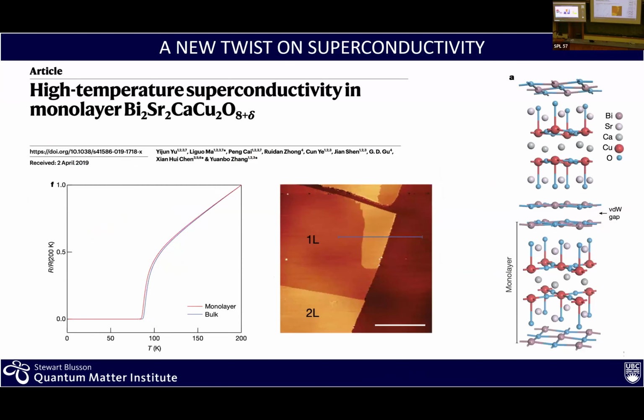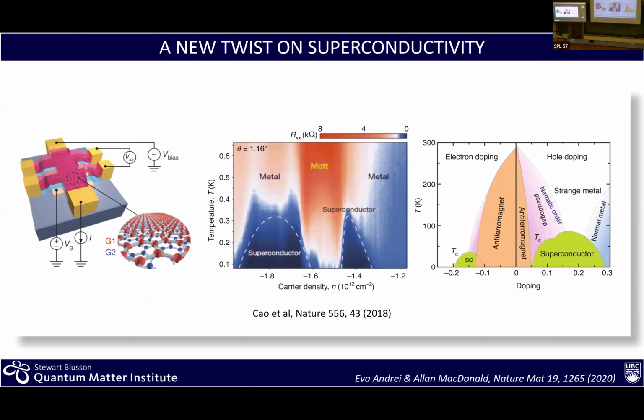Well, after this, another major discovery or breakthrough was obtained. This is, yes, please. I assume that in the cuprates, as you lower temperature, the antiferromagnetic phase resistance is very, very high. Is extremely high, yeah. On this graphene, it becomes small resistance at the temperature in what's supposed to be the insulator. Like between the two superconducting.